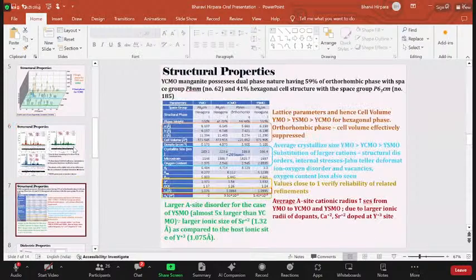Now we have obtained some structural parameters from the Rietveld refinement method. YCMO shows two kinds of phases, hexagonal and orthorhombic: 41% hexagonal and 59% orthorhombic phase, showing the Pbnm space group as well as the P63cm space group, number 185. Also, from the cell parameters and the cell volume, we can see that with 10% doping at the yttrium site, the structure gets disturbed. Talking right now about the hexagonal phase, the cell parameters A, B, and C decrease, and the cell volume also decreases as we go for the doping.